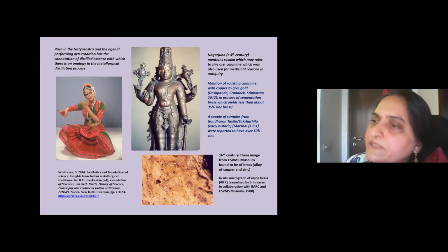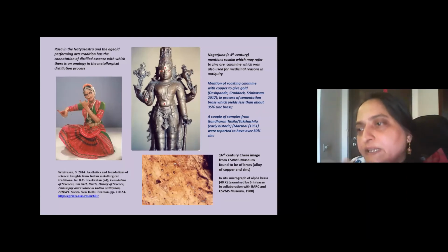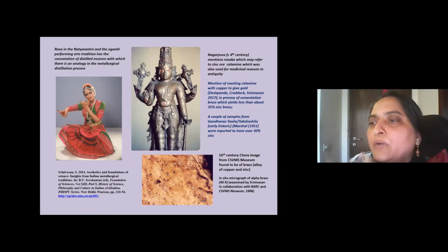And the use of cementation brass was also known, for example, in the Roman world, where they called it aurichalcum and so on. But what was interesting is that with cementation brass, there is a limit to the amount of zinc that can get into the brass, because it is an alpha brass. So it doesn't have more than about 35% zinc in this type of brass.